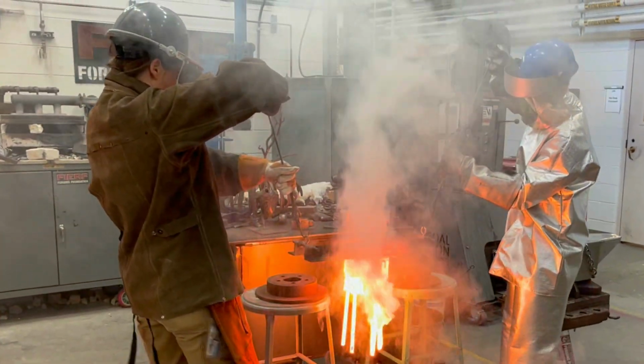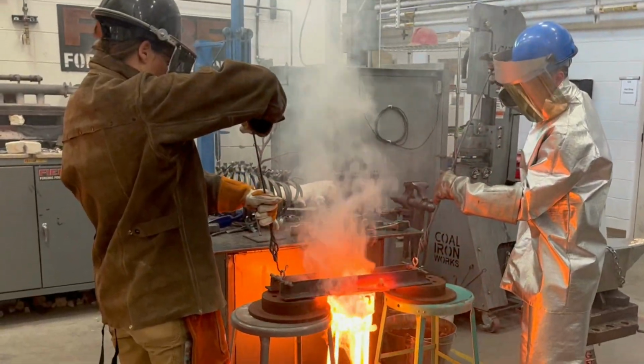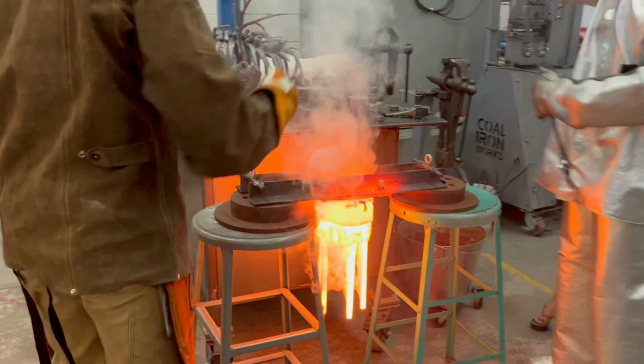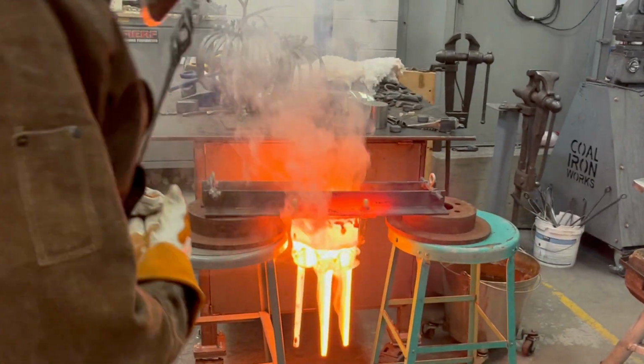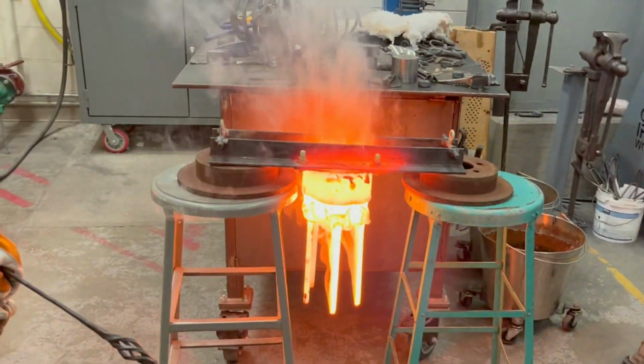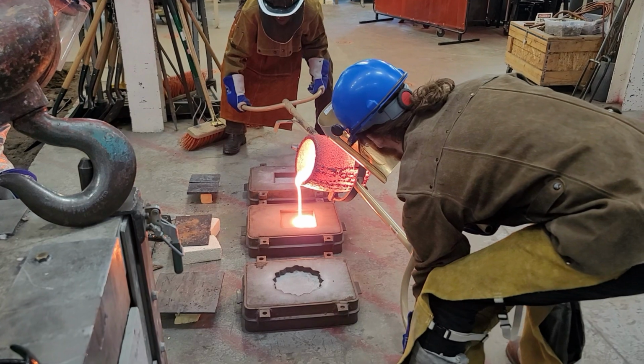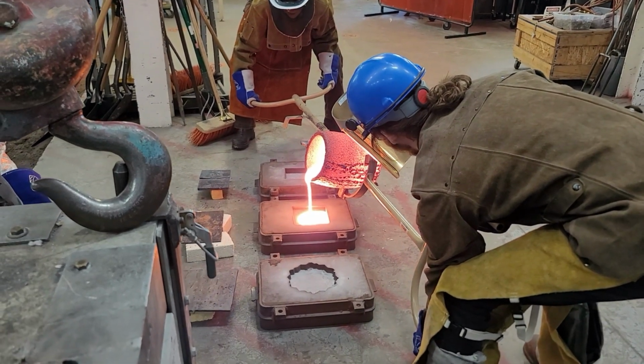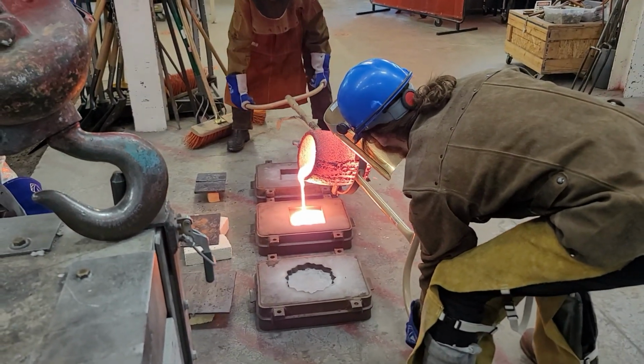After removing it, the team observed that all 4 rods remained within the housing and appeared to maintain most of their section. The rods were then left to cool and then were set aside for post-mortem microstructural characterization. And then the remaining molten regolith simulant was poured into the crucibles and left to cool at ambient room temperatures.